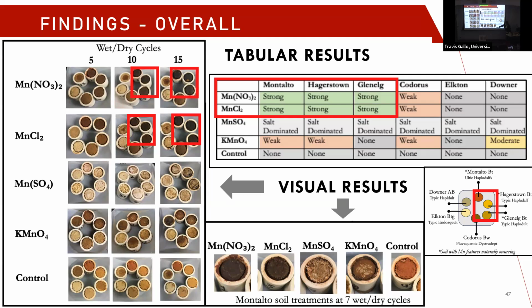I provided you some close-ups of the Montalto soil treatment at the 7 wet-dry cycles. The 3 columns there show the wet-dry cycles at 5, 10, and then 15, and you can see that they get progressively darker with time for those results where they were exceptionally dark and well expressed.